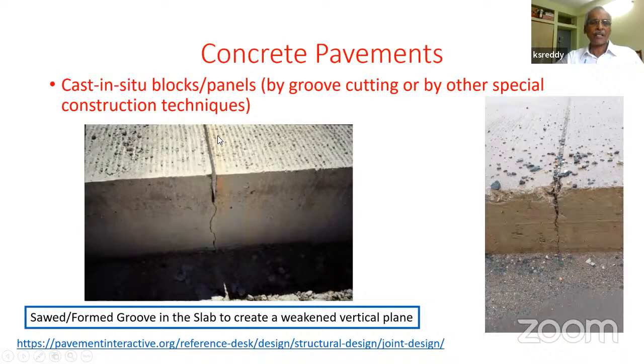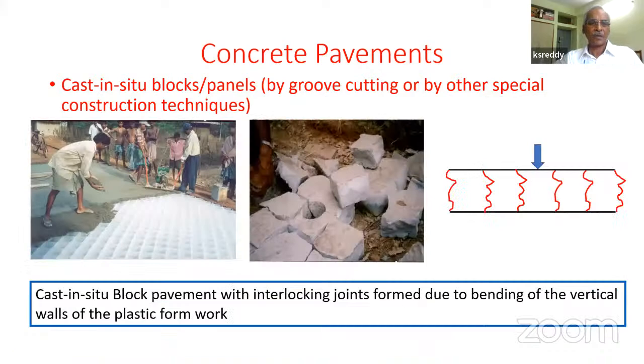On the other hand, we create those joints by pouring concrete and then cutting grooves here. For example, this is a transverse groove that we cut up to 1/3 depth of the slab. And we expect a crack to form below the groove. So once you have a groove, this panel is separated from the adjacent panel. So a groove and the crack formation below that ensure that you have panels of the size that you created, maybe 4.5 by 4.5, 4.5 by 3.5, whatever is the joint spacing that you consider, transverse and longitudinal. Okay. So this is a common form of joint creation that we do on national highways. But let us see the implication of this.